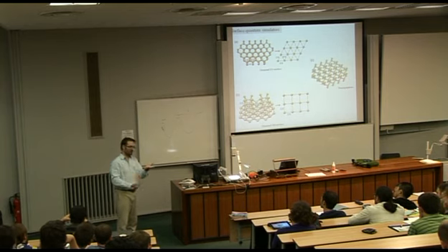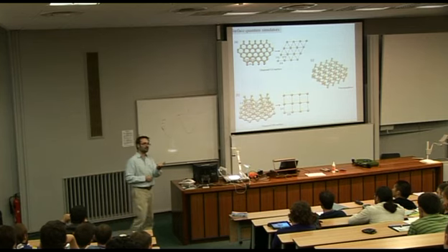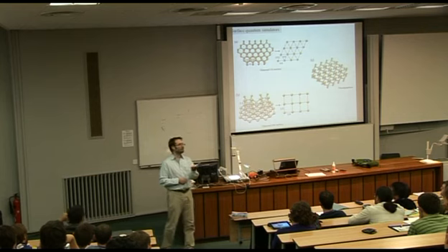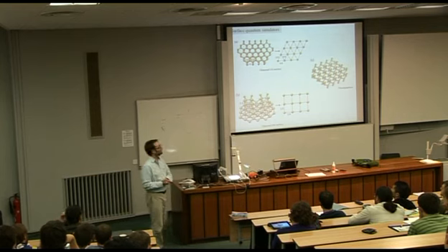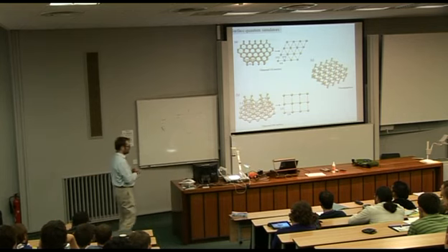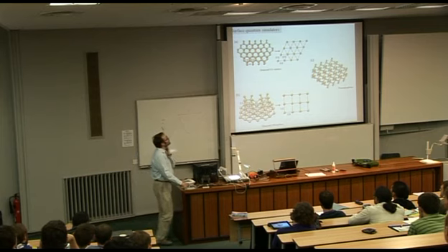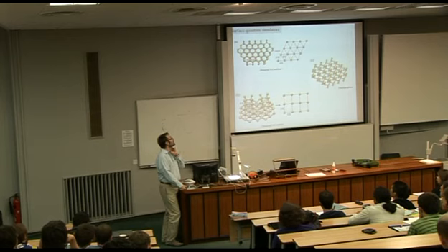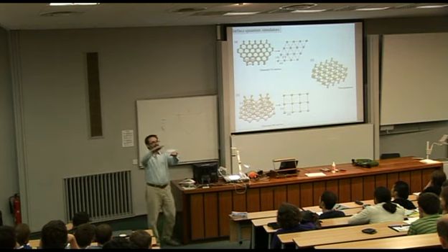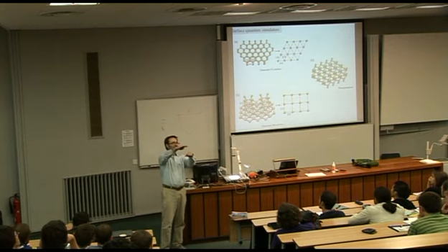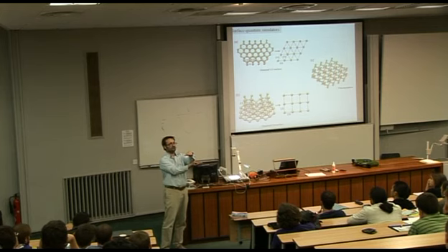And so actually when you have an NV center underneath a sheet of graphene, you're not going to see it. And you cannot manipulate it with light, and therefore you would have a real problem. Then we fortunately discovered that Novoselov and Geim, the guys that made graphene a few years ago, created fluorographene. So it's graphene, and it has on top a layer of fluorine, and on the bottom, underneath, a layer of fluorine.